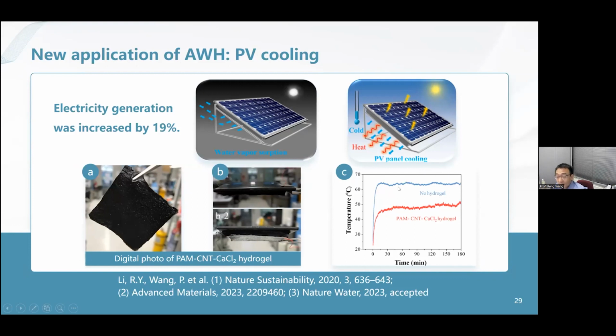Now, what happened is what I presented in this figure C. You see, with this hydrogel on the backside of the PV panel, the temperature of the panel can be reduced by more than 15 degrees Celsius as compared to the one without this hydrogel. Well, it's actually very simple. This material absorbs water vapor from air. During daytime, when the panel is heated up, the heat is transferred from the panel to the hydrogel on the backside. Now the heat drives water to evaporate out of the sorbent.